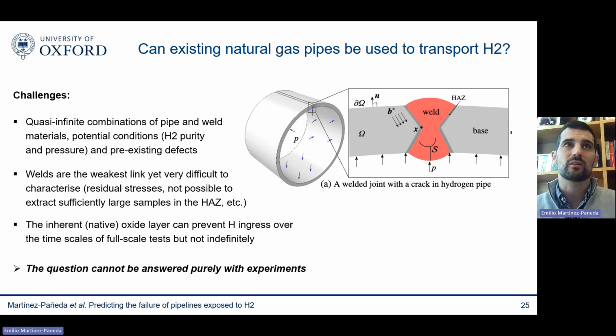And the weakest link are going to be the welds. And that's a problem because, of course, we are thinking about pipelines that have been deployed over decades, since the 50s. So we have an almost infinite combination of pipe material, weld condition, and also, of course, pre-existing defects within the assets, residual stresses, and also conditions that we are considering, right? We want to consider different hydrogen gas purities, different pressures. So this is an almost infinite combination of all these things. So it's quite difficult to test in lab scale all these combinations.